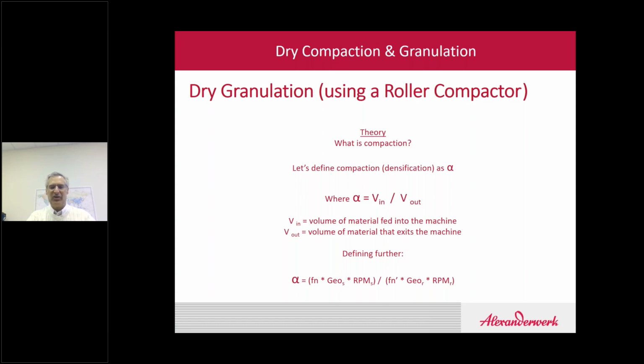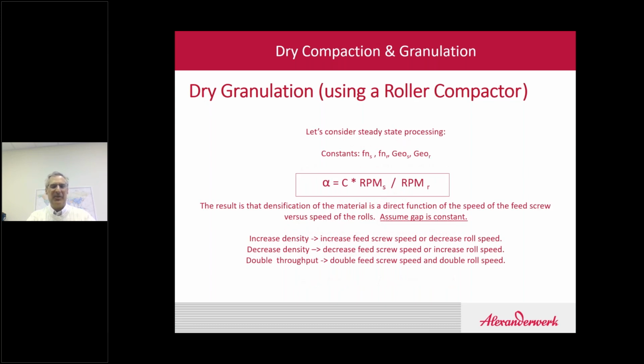If you want to start looking at this in terms of all kinds of mathematics, we can throw in a couple of geometrical designs and speed designs. And basically what it comes out to be, I'm simplifying this in the interest of time today, is that alpha is a function of the feed screw speed divided by the roll speed times a constant, assuming the gap is held constant. So if you want to increase the density while the system is running, you could increase the feed screw speed or decrease the roll speed. If you want to decrease the density, you could decrease the feed screw speed or increase the roll speed.